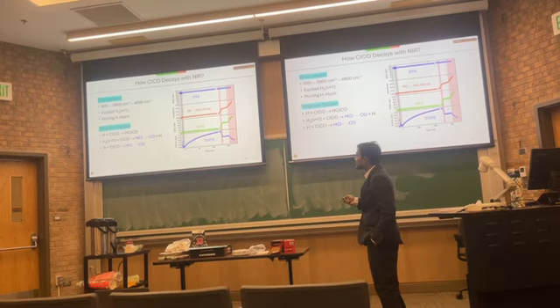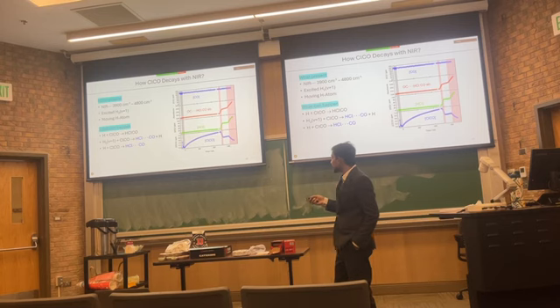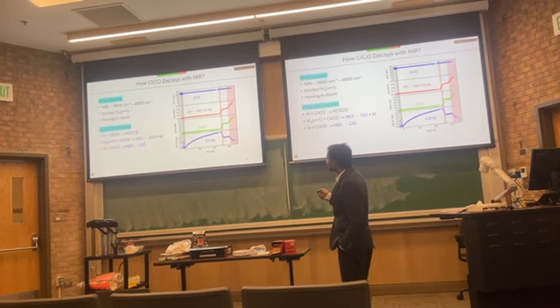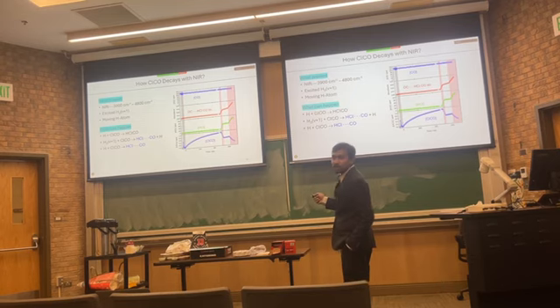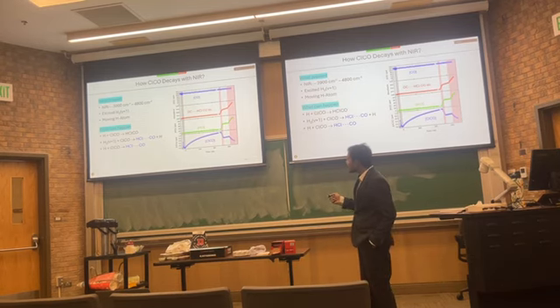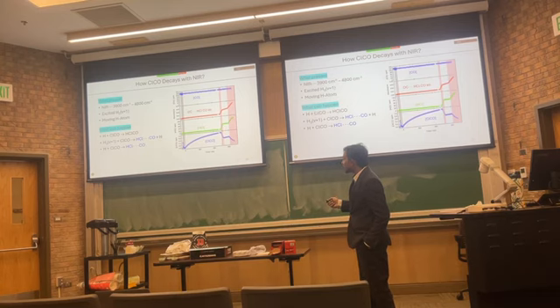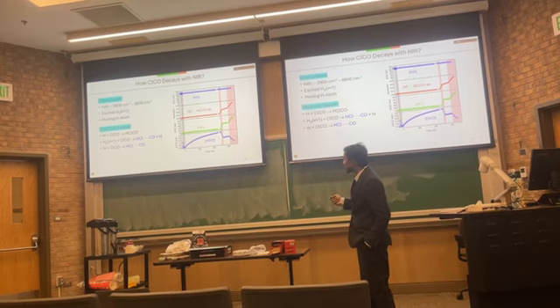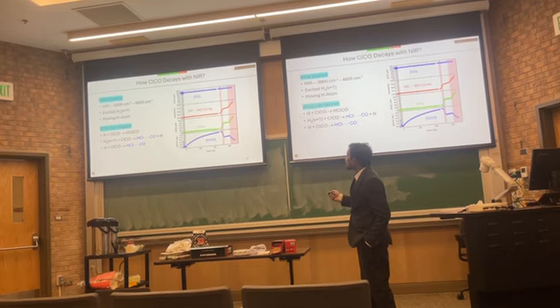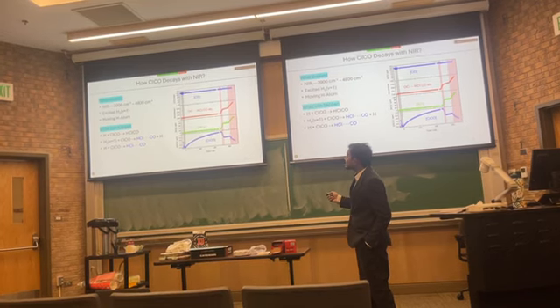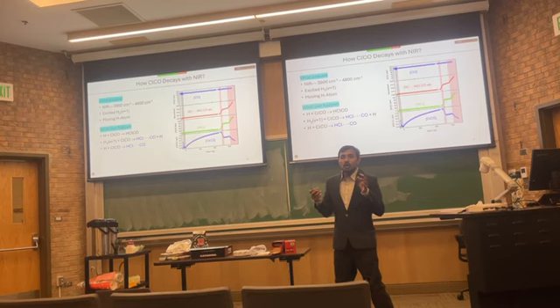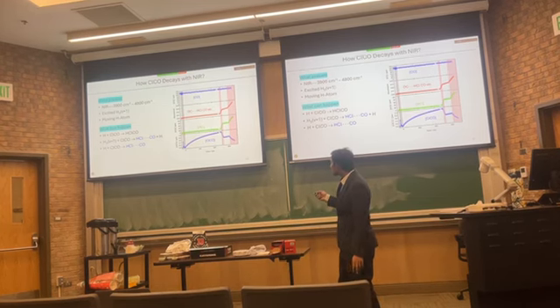Again, this is photolysis, and the red bars are near infrared. So what's happening here? This is CO, this is HCl, this is ClCO, and these are the cluster peaks. Here I'm showing just the absorbance. We're seeing our normal ClCO growth. When we expose it to near infrared, it starts to decay. When it starts to decay, let's look at what happens to the HClCO state. We see that HClCO is growing.